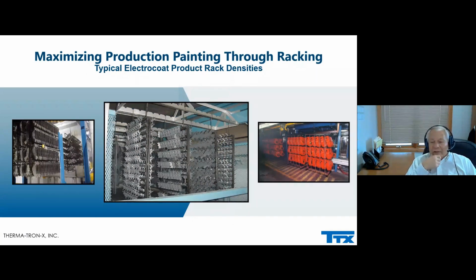Here's the kind of rack densities that you see. On the right-hand side is a single one coat for the outdoor garden market. Those are actually engine covers. They're laminated, a process basically for sound deadening, and they do a two-color application with a 50-50 split. Here you see high rack densities for products that are loaded going into the electrocoating, and different rack styles for a load bar that goes through pre-treatment, immersion process and electrocoating. That's a typical rack density.